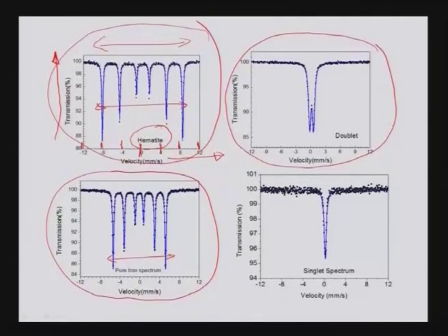This spectrum is a 2-line, a doublet spectrum, and this results when the solid has a non-cubic crystal structure and is non-magnetic as well. Magnetic will split in 6 parts. This is the kind of spectrum, for example, for iron in clay or iron in some compounds, iron carbonate and other things, or olivine or pyroxene. Yesterday I was talking of Fe2SiO4 olivine.